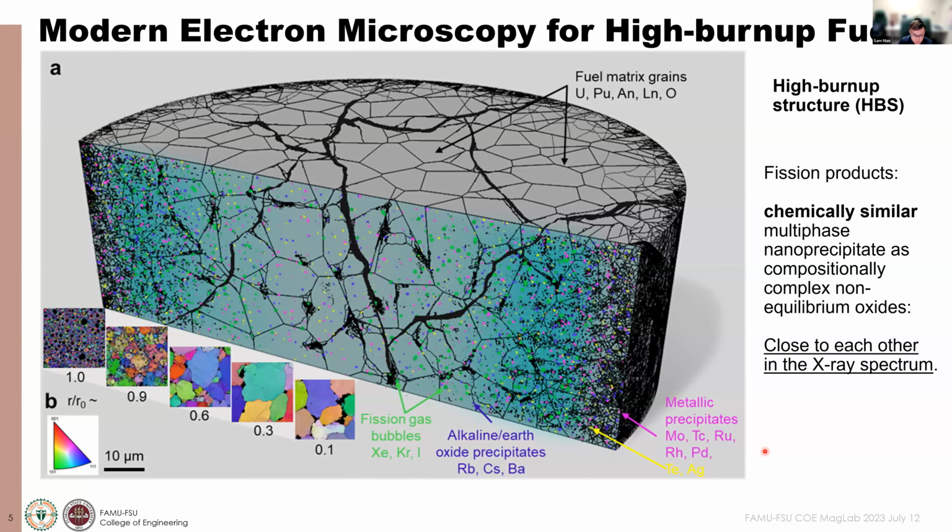What we are looking at is the periphery of these fuel pellets. You see these segmented regions. These are not artifacts; they happen because at the periphery, because of the diffusing gas bubbles, we are reconstructing the grain boundaries near the periphery of these fuel pellets.